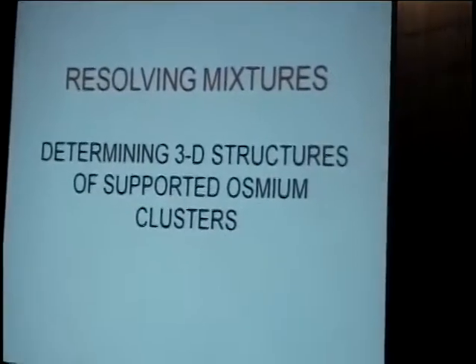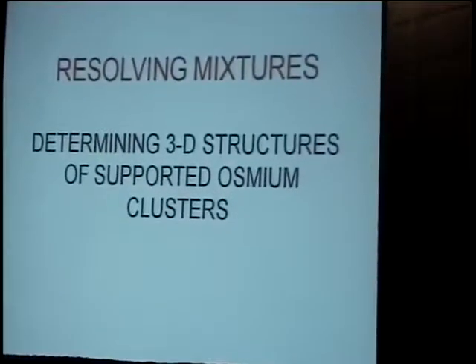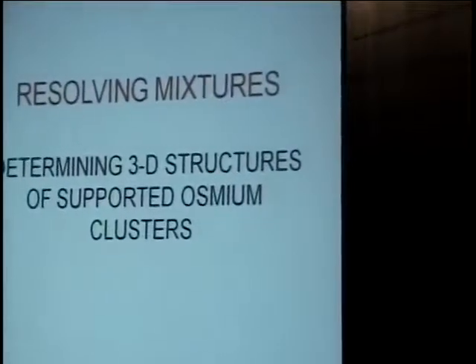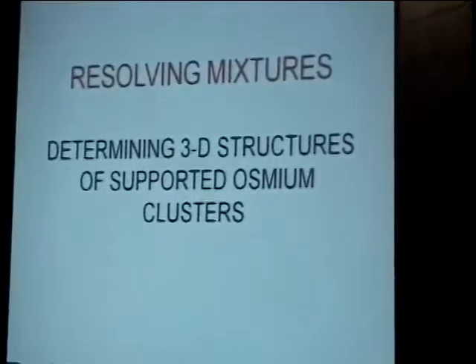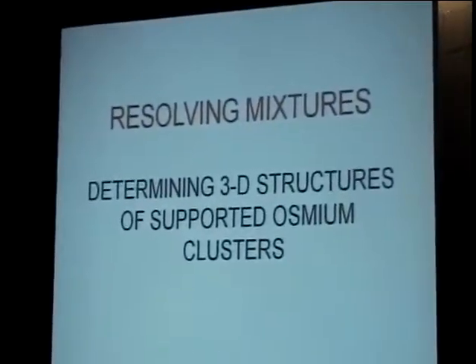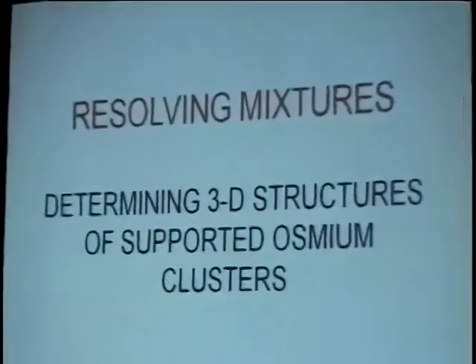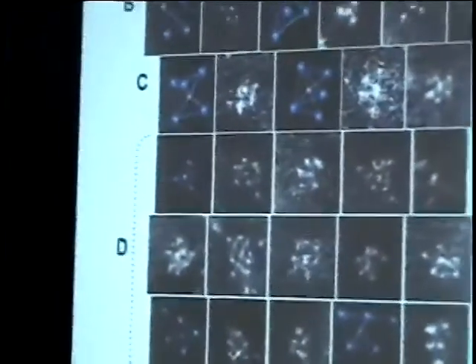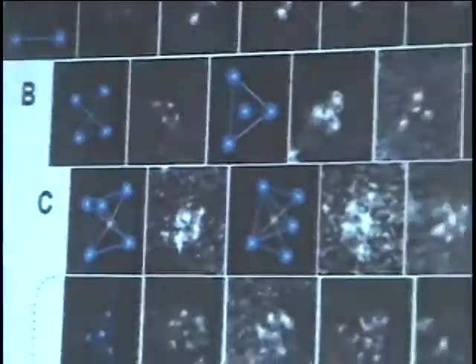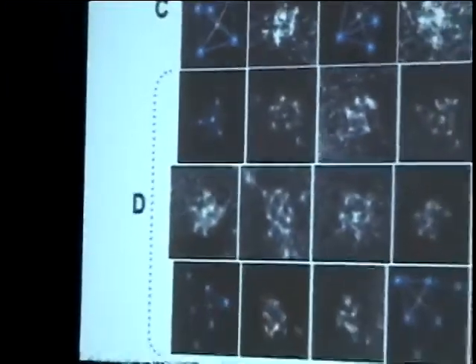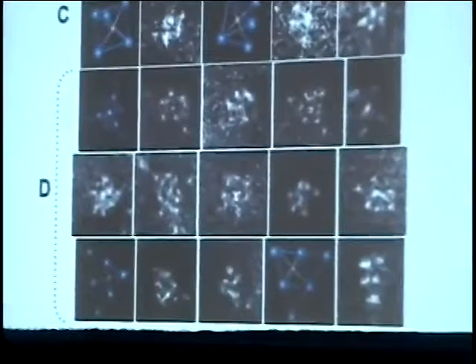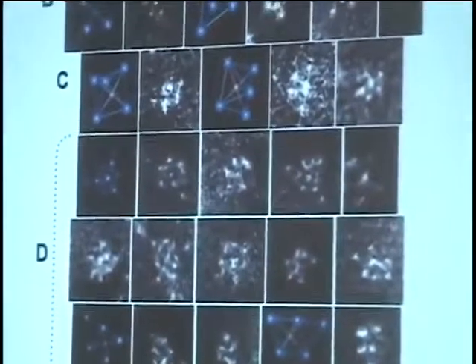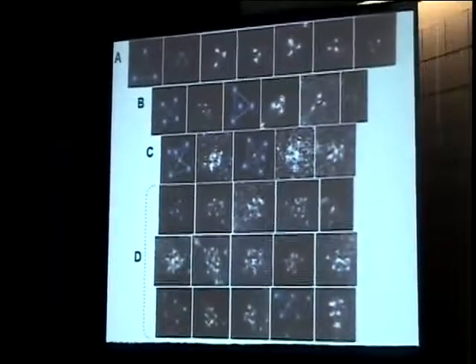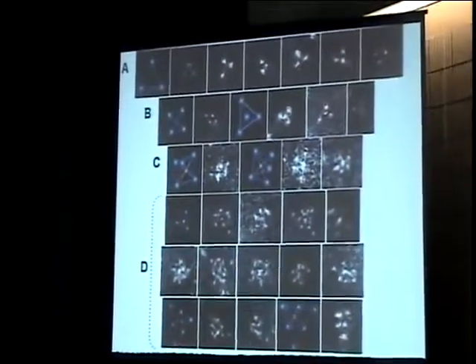So we're taking a step towards the complexity of industrial catalysts, but it's maybe you would say a small step, because the clusters are still going to be small, and the complexity in terms of structure is not going to match that of a typical industrial catalyst. So what we've done is we've taken a sample, made it from the triosmium cluster, treated in helium to fragment the clusters, as I mentioned before, then treated in CO to start forming larger clusters, and we chose the conditions to get a mixture. So not just Os10 or Os5, but a mixture. And then looked at that sample in the aberration-corrected STEM and analyzed a whole bunch of samples.